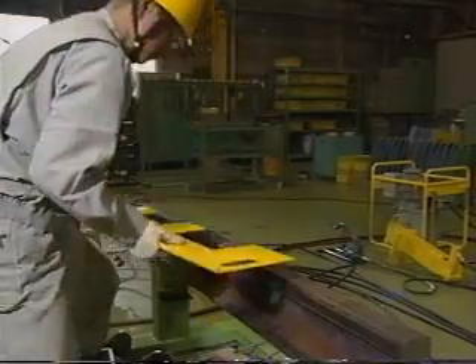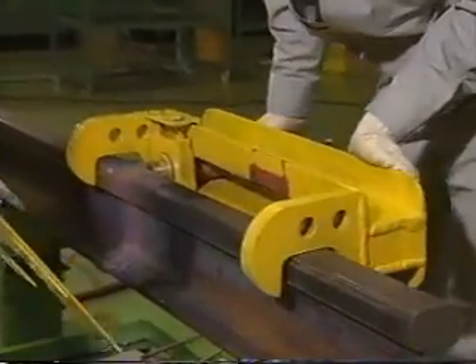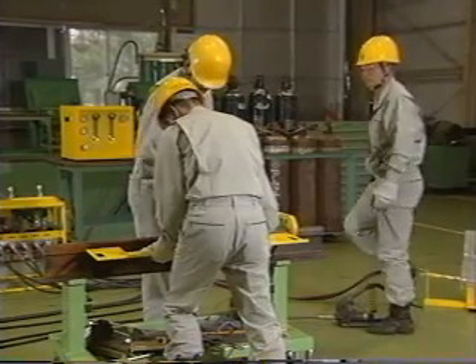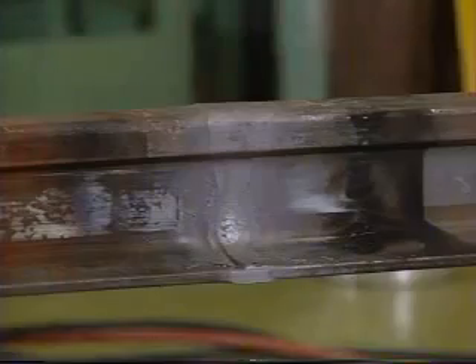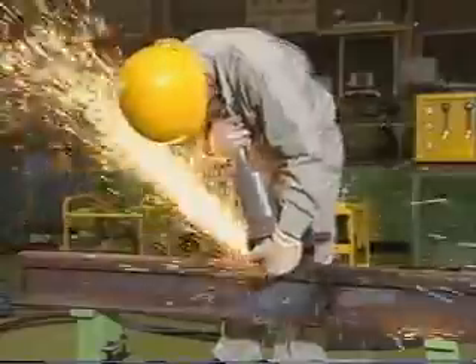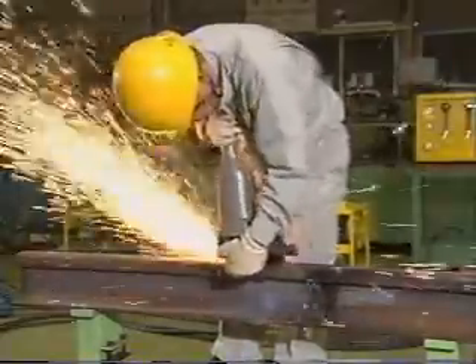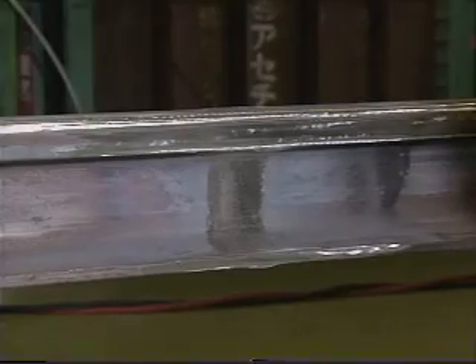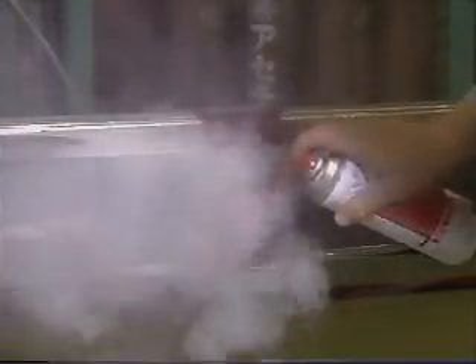Remove the gas pressure welding machine and measure straightness and bend. Bends must be corrected vertically and laterally if necessary. This is important for quality assurance. After cooling, finish the rail surface with a grinder. If you weld heat-treated rail, you need post-heat treatment. Gas pressure welding work is completed with the final inspection by a penetrant test or a magnetic particle test.